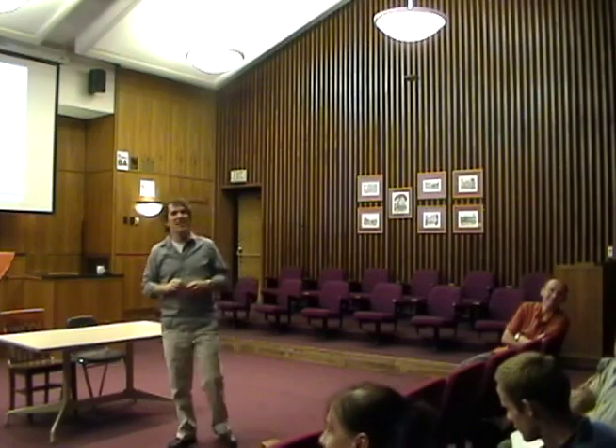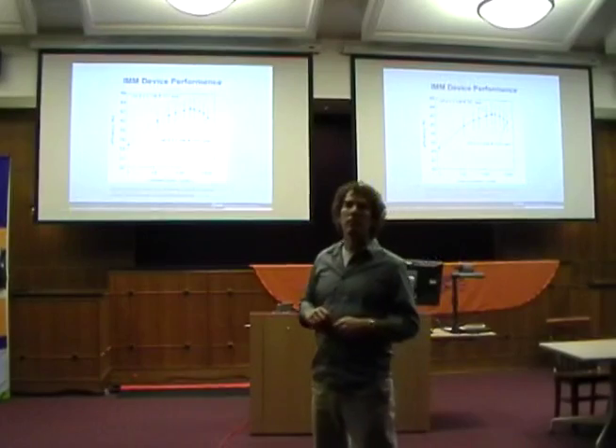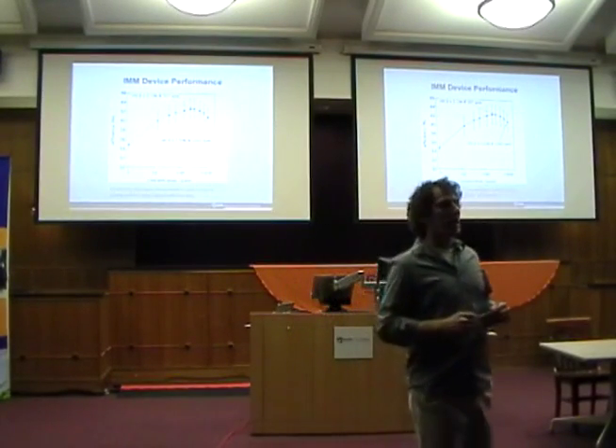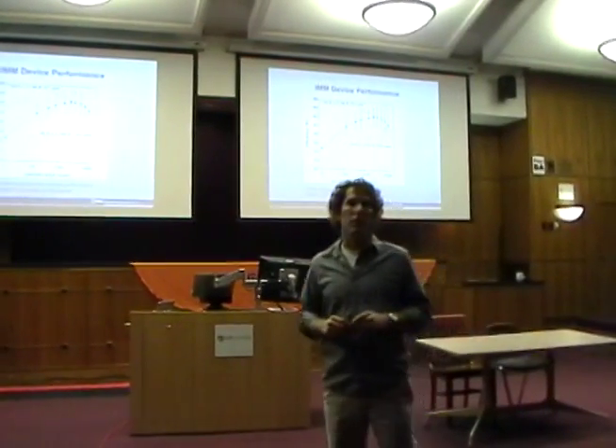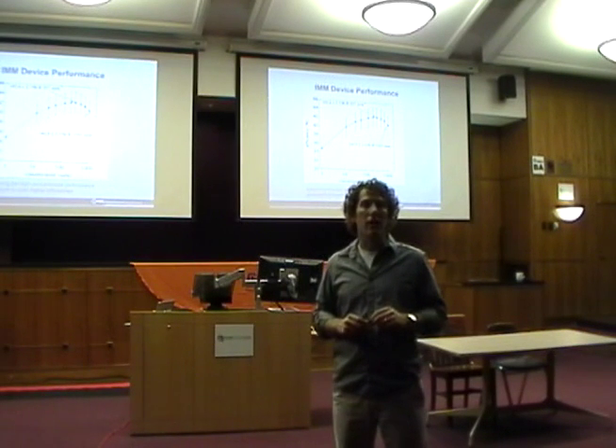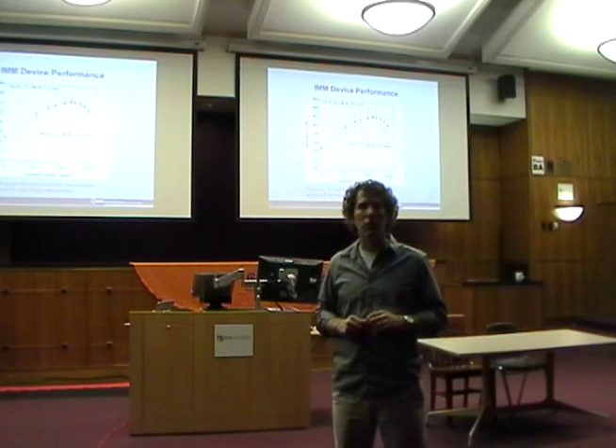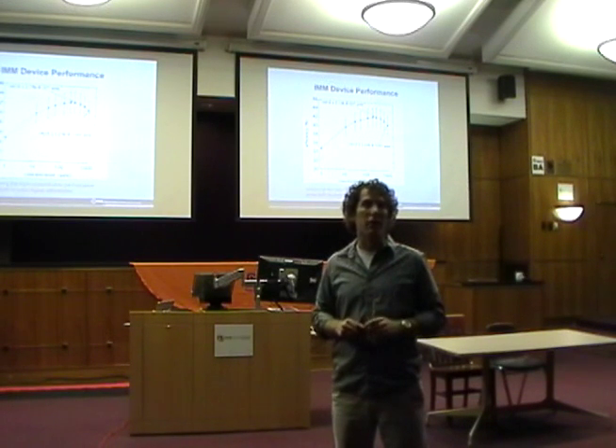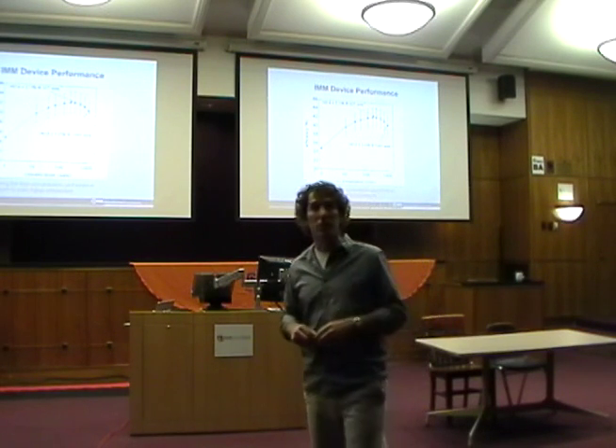So you're talking about optimizing the metal grid on the top. What would happen if you used a transparent conductor for the top contact also? If you had a good transparent conductor, that would be great. There's been some research into that. The best TCOs, I think, have a transparency of about low 90s percent. That's not high enough. That's a 7 or 8% loss, you're done. So if you can figure out how to make a TCO that has 99.5% transmission and good conductivity, you'll be a billionaire.